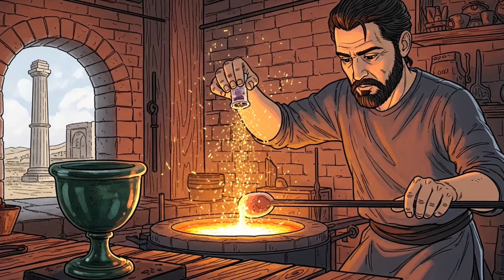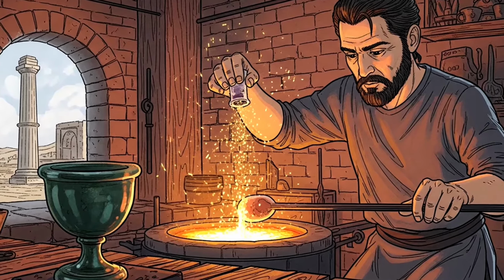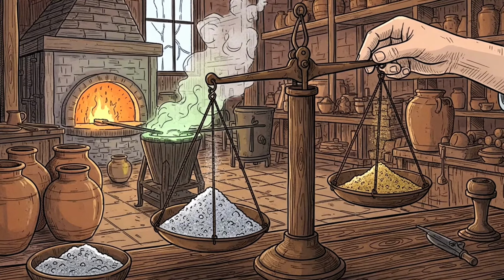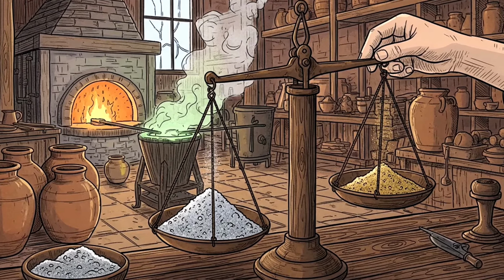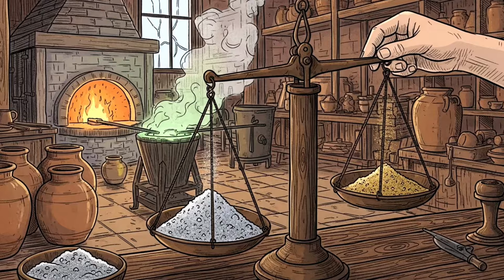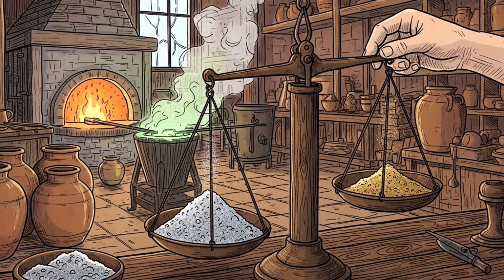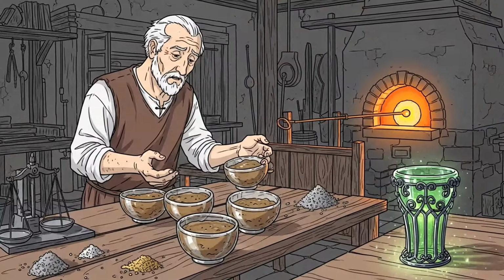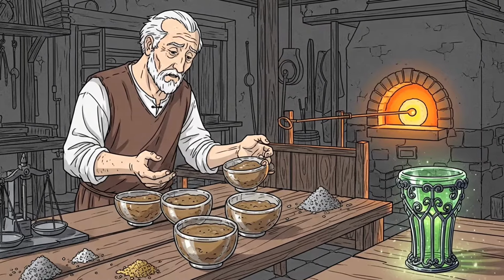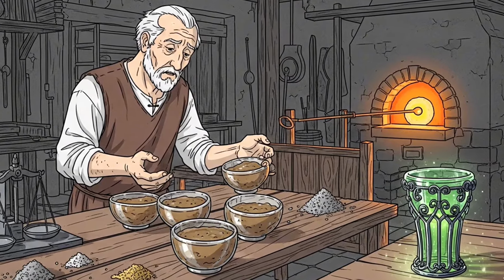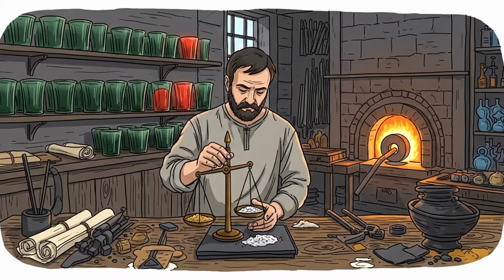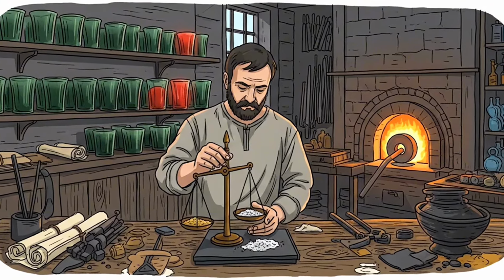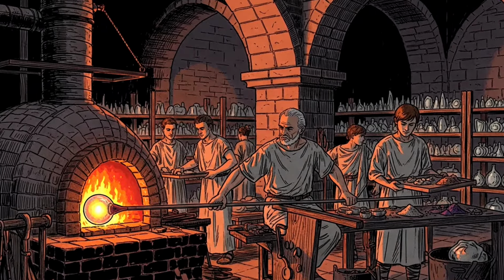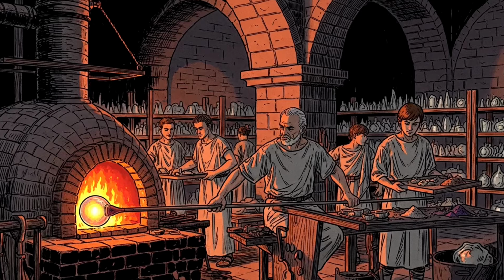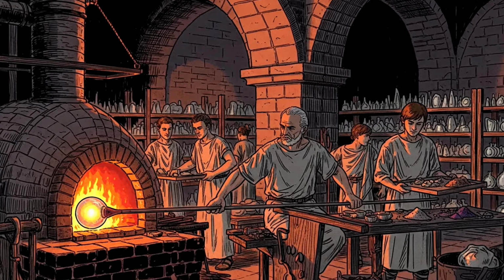The precision required to achieve this is remarkable. The silver to gold ratio sits at approximately 330 parts per million silver to 40 parts per million gold. Any significant deviation from that ratio produces muddy, non-shifting glass. The consistency of the effect implies that this was not a lucky accident. It points to a specialized guild of Roman glassmakers who had mastered exact heating and cooling cycles through generations of